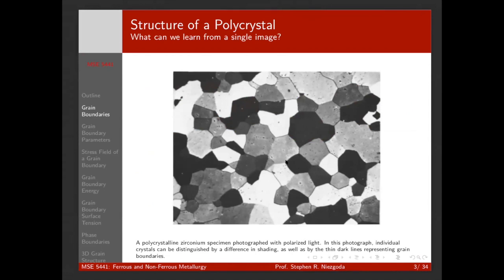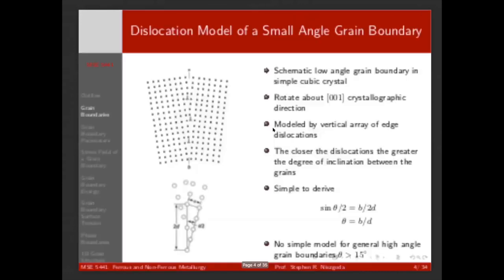We see that grain boundaries are generally straight, and our grain boundaries and triple points tend to make 120 degrees. If we saw a grain boundary that deviated significantly from 120 degrees, we might speculate that one of the grains that met at that triple point had some kind of special energy, with either a lower or higher grain boundary tension than others. So there's a lot we can tell by looking at this structure.